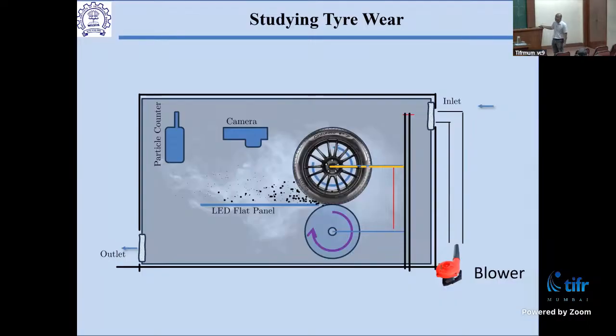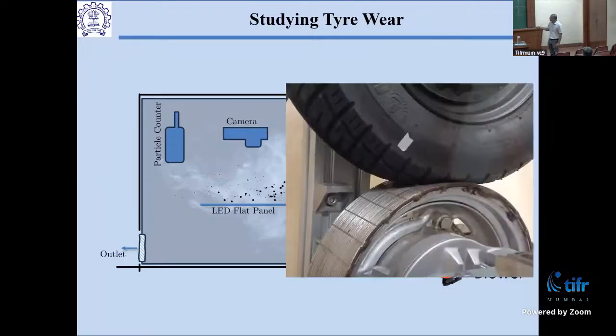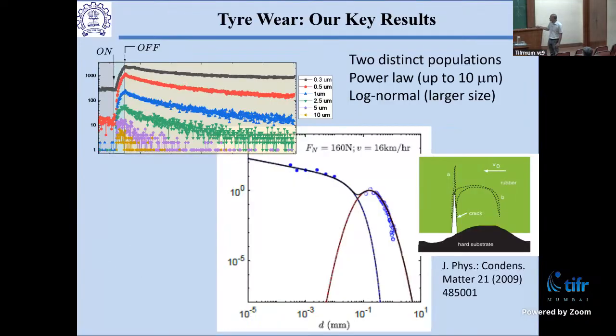plexiglass box in which this is kept, is that there's so much dust everywhere in Mumbai that before we run this experiment, we have to clean up this thing, right? And so once we clean it up, that's my baseline level that I get for the aerosols. And then when I turn it on, it jumps up by typically about an order of magnitude. We let it run for 10 minutes and we do it for a short time so that the tire doesn't heat up. So everything is done isothermally.